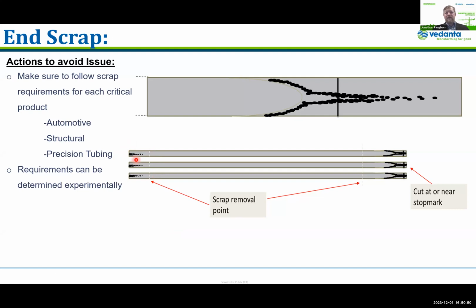I feel like on most presses I've seen, 2, maybe 2.5 inches, 65 millimeters is probably about as far as you can go on basically any shape, or else it's really just going to pull out and leave voids in the air pockets in the die, which are then going to result in blisters. There are some things you can do in die design to make it difficult for the metal to pull out of the ports, by putting some tapers in there. But even so, that doesn't get you a lot. You're not going to be able to shear a 4-inch, 100 millimeter butt and get good results.